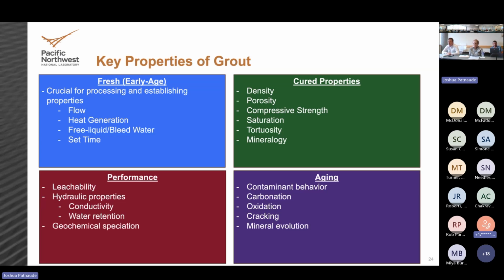But if you're going to a disposal site where you have a pathway to the biosphere or a pathway to groundwater, like the Hanford IDF, you're concerned about long-term leachability. How long, or what does that 1,000-year term look like? And the way we study that is we try to make links between short-term tests where we can screen materials in the laboratory to longer-term laboratory tests to very long-term field tests to looking at things like natural analogs.